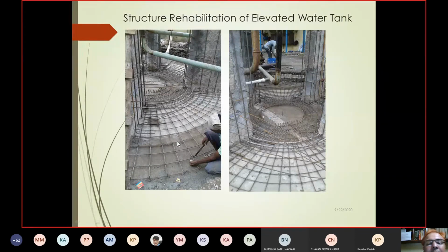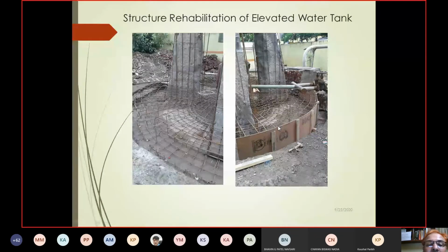Here is the 10 mm bar on both sides, and here in the center we decided a spacing of 125 mm, and here is more and here is less, and in distribution steel also we adopted the same spacing. And this is the L bar, which we started for the jacketing. For jacketing, this bar is in this foundation. This is the single layer of this mesh. In the next slide we can see this is a double layer. After the single layer is completed, this double layer is there.